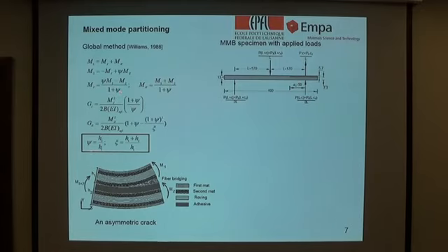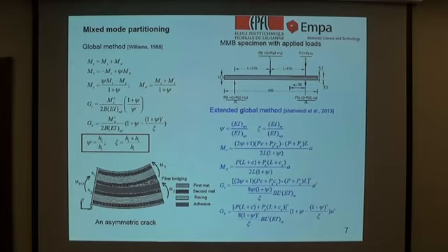And in our case, it's not easy to use this because it's not only a geometrical problem, because the material property for each layer is different and it is not isotropic. So we have changed these two to the equivalent elastic bending moment and replaced the equation. So these are the two new equations that we use to separate mode 1 and mode 2.